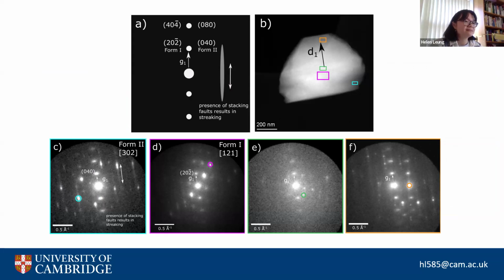But the 4D STEM data shows quite an interesting story. So here we have 4D STEM data taken on our Spectra, Thermo Fisher Spectra, on a Merlin camera. We have just a 256 single chip. And you can see that there's some sort of streaking in this direction that I'm highlighting with arrows, and I've got a schematic here as to the direction of that streaking. And what we found is the direction of that streaking is parallel to the G vector that corresponds to these very strongly hydrogen bonded stacking of the layers. So we know that these layers stay relatively invariant, but that they can shift around each other. And so the streaking is an indication that these layers are actually indeed not very rigidly defined, but they are shifting around. And the SED basically reveals the presence of this. Sorry, when I say SED, I do mean 4D STEM. SED is another word that we use for it, which is scanning electron diffraction.